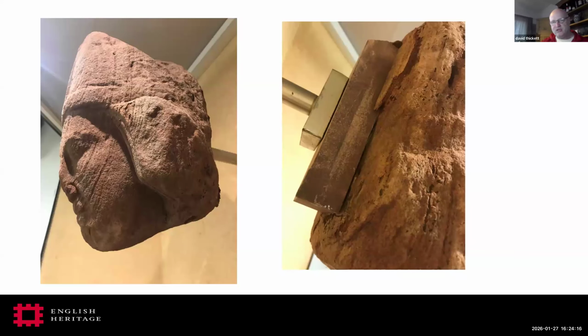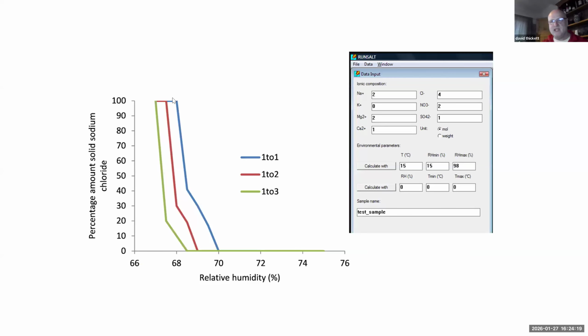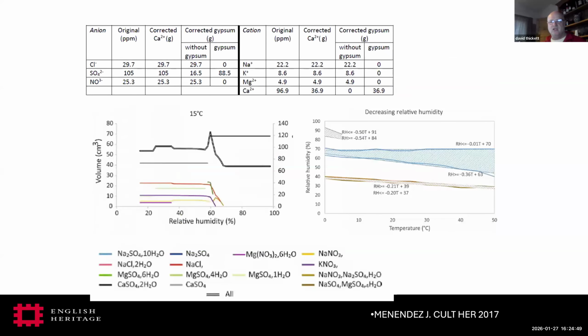But once we've got those salt and ion concentrations, as we see here, we can feed them into a thermodynamic model. This is something that was developed by a European Union project, and it will predict at a particular temperature what happens when we pass certain RH thresholds depending on the concentration of the ions. And you can see somewhere between 70 and 67 for sodium chloride and sodium nitrate, that will occur. And if you do a lot of these calculations at different temperatures, you can build this kind of stability diagram of temperature against relative humidity. The white regions are safe. If your temperature relative humidity starts going across these boundaries, you will get salt activity.